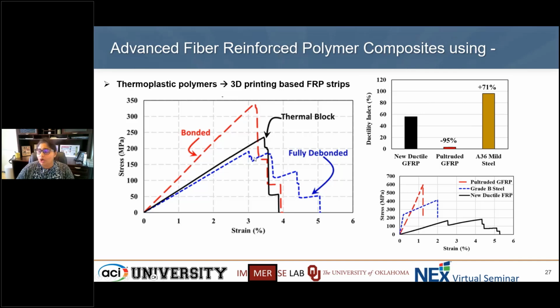In a different unique bond where you have no bonding between these different orientations, you have a very good improvement in the progressive failure, where basically that delayed failure is going up to 5%, although at a compromised strength and stiffness. So the target would be, if 3D printing is really so effective in achieving delayed failures, the ideal situation would be with 3D printing to achieve that kind of a unique bond between these composites, where you have a non-compromised strength and stiffness, while providing that delayed failure mechanism or progressive failure mechanism.